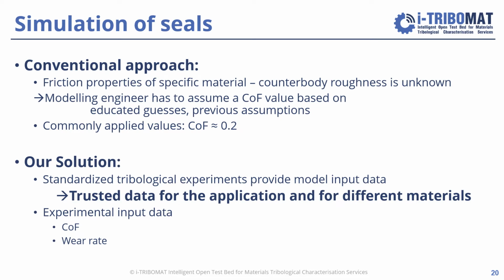Our solution is not to assume such a critical input value, but we want to measure it. And we can measure it in the tribological experiment. For that, we set up a model test which is standardized, which is done in the same way each time, well documented, and the output of this tribological experiment is well defined, and this is used as an input data for the simulation. And because we have it all in one hand, the simulation and the tribological experiment, and also how the data of the tribological experiment are processed in order to provide an input value for the simulation, we trust it, and we know exactly the quality, and we know that we're doing it the same way each time. So we offer a trusted data for the application for different materials.